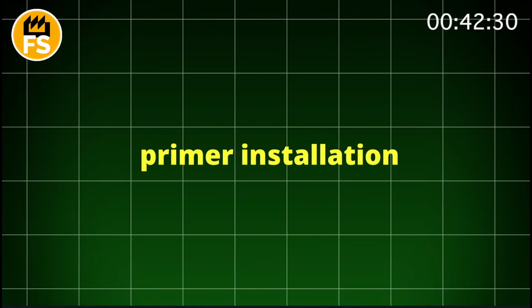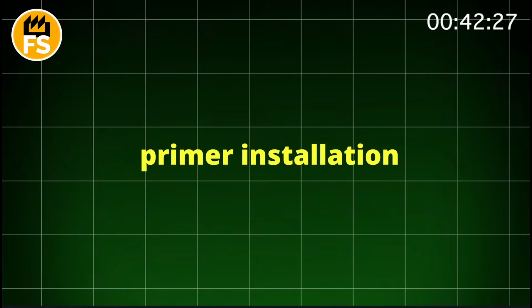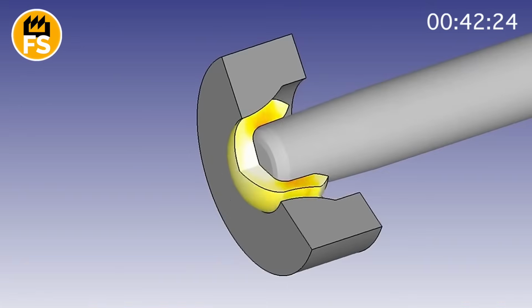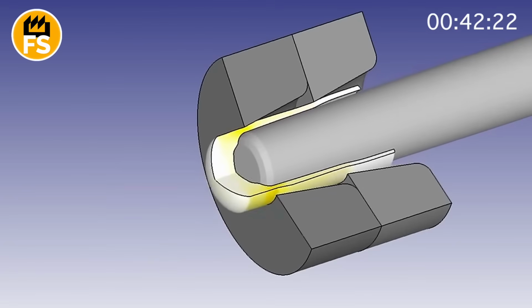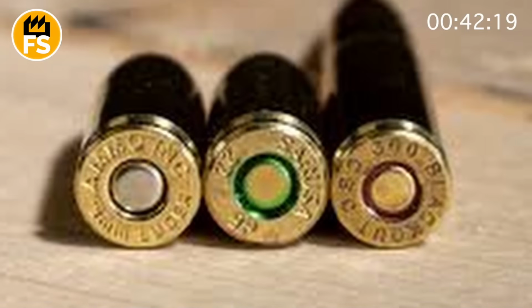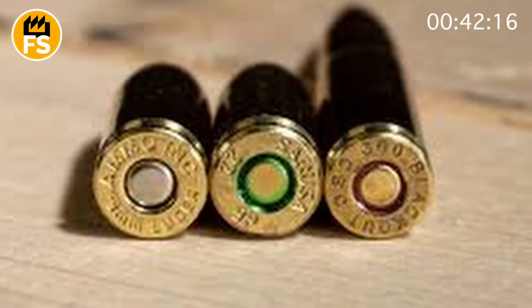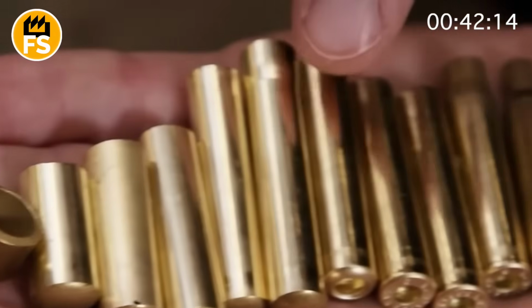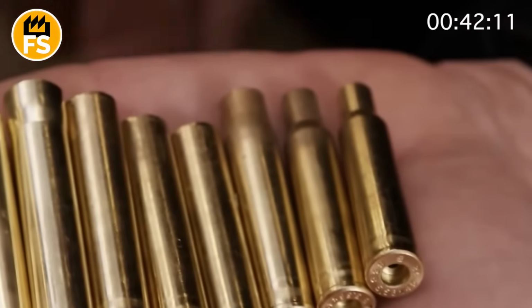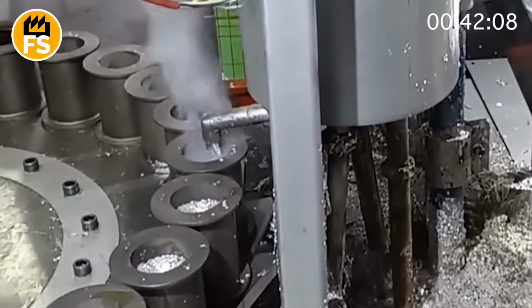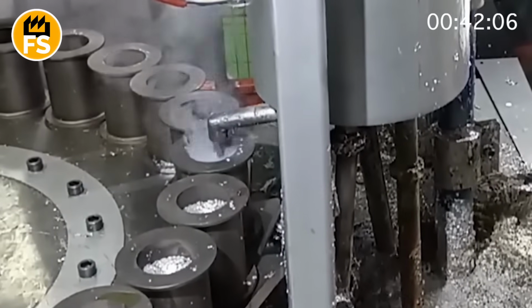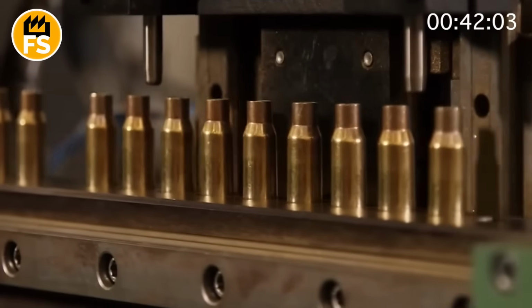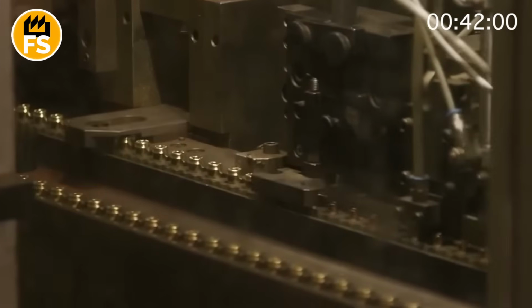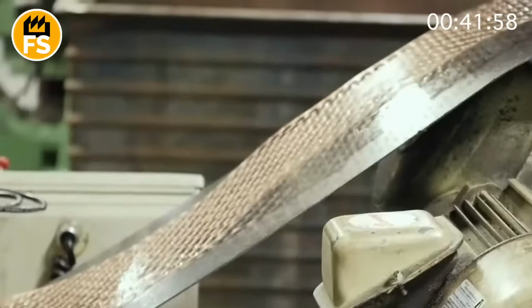The next critical stage is primer installation. This is a small but extremely important component that initiates the explosion. The primer is a miniature explosive device. Inside a metal cup is a primary detonator, usually based on lead styphnate or lead-free substitutes. Before installation, primers are checked for sensitivity. Those that react to a weaker impact or have an unstable explosive concentration are rejected. On an automated line, each casing passes through a priming station where, with incredible precision, a mechanism inserts the primer into the rear of the casing and crimps it so it doesn't fall out during recoil.